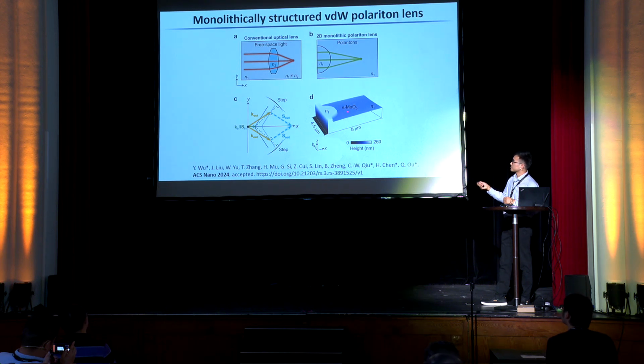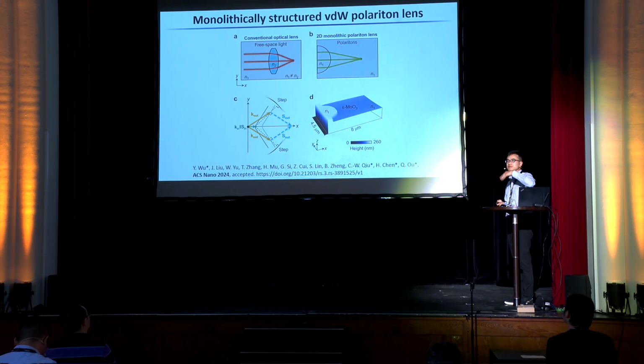For example, you can see here, this is a higher thickness. We use photolithography to protect this area, and then use RIE etching to reduce the thickness of MoO3. The surface is quite flat, so it is a kind of layer-by-layer thinning. But obviously, some reviewers did not like our idea, which we originally submitted to Nature Photonics.